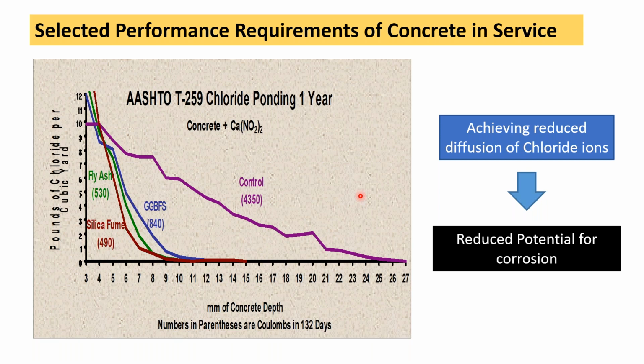And this is where slag perhaps is most beneficial, is in achievement of diffusion control, because slag added to concrete has a tremendous chloride binding capacity. And if you look at, these are the tests of chloride penetration obtained from the chloride ponding test. This is the chloride profile in control, which is normal concrete. And by the time I add blast furnace slag, you see the profile is limited only to the surface layer. And of course, also fly ash cuts this down. So these supplementary cementitious materials are helping on several fronts. One is improving the durability in the form of shrinkage, heat, and also chloride penetration.